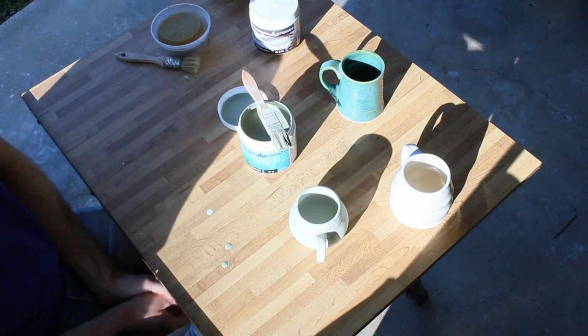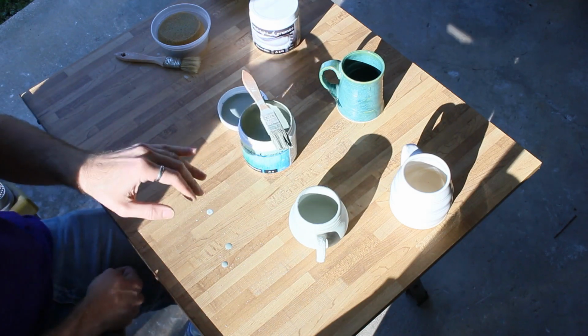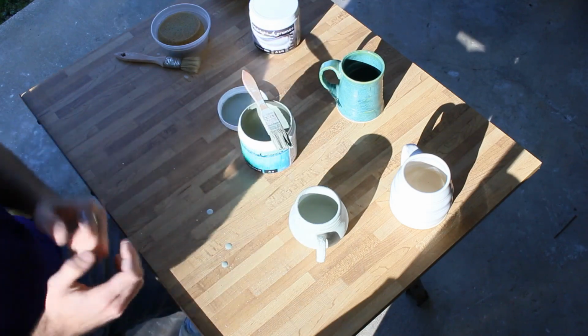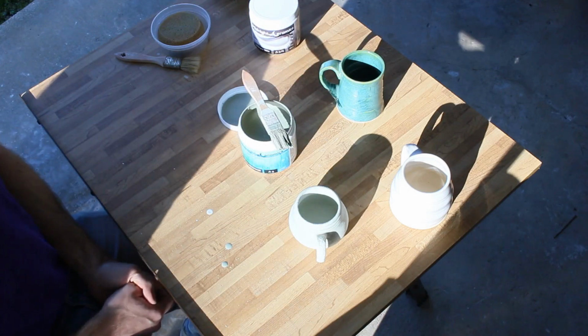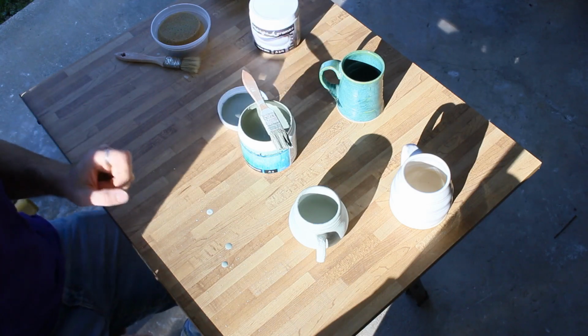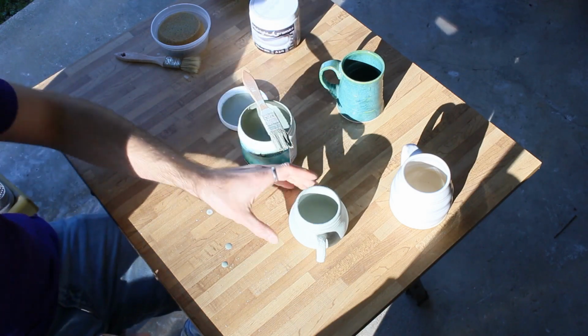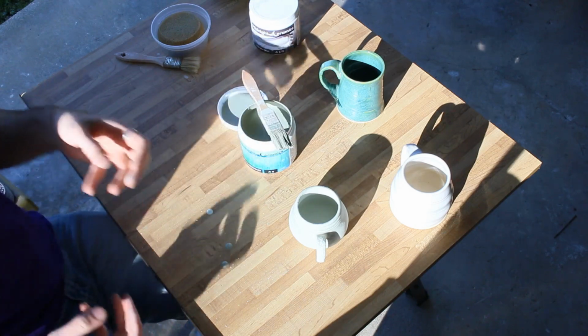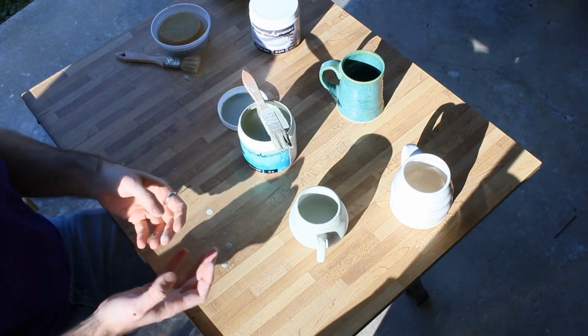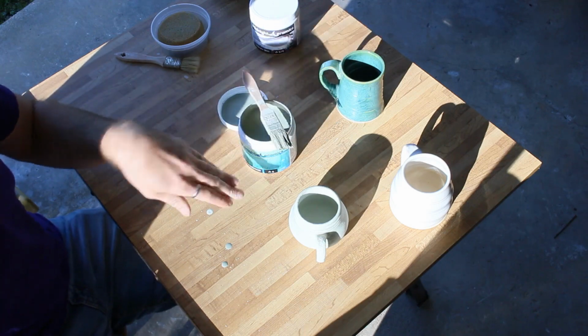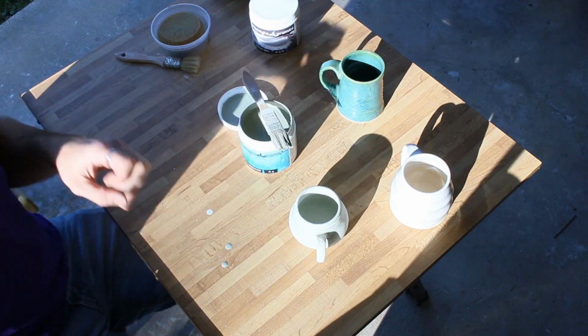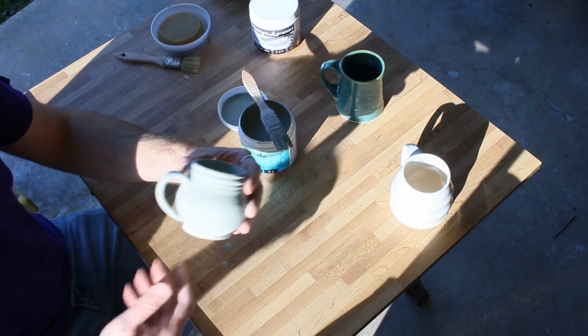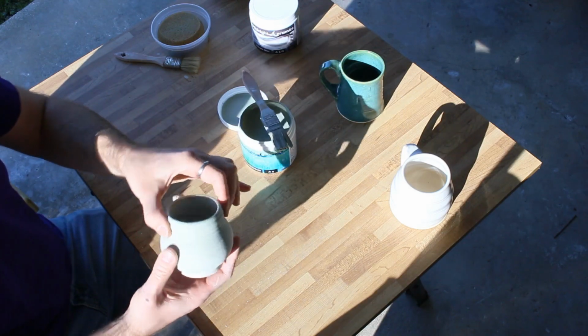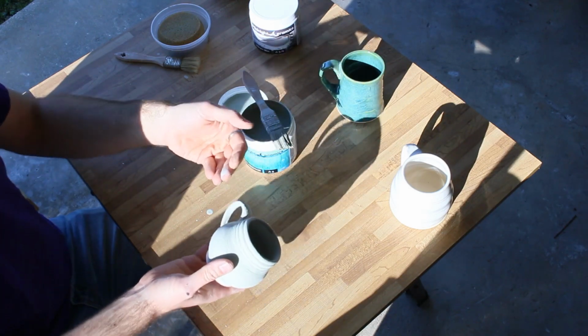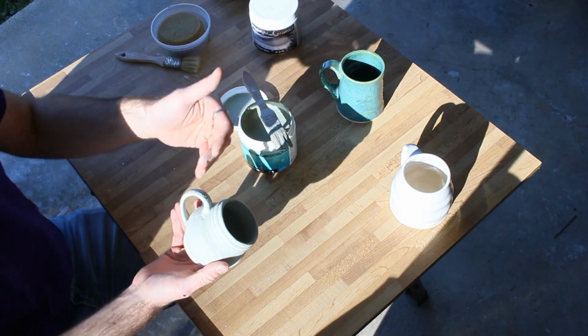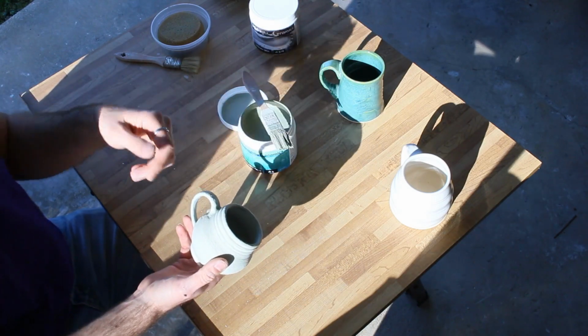So that's applying 1 glaze to 1 pot. I can talk a little bit about glaze defects as well, specifically trouble that you might run into while you're applying glaze to a pot. The biggest one that I tend to see is called crawling. And with crawling, what happens is people are applying way too much glaze to their pot, or for whatever reason, the water from the glaze isn't able to soak into the clay. So if it takes more than like a couple minutes for your pots to be dry enough that you can touch them, then there's probably too much water in the wall of the pot, or there's wax there, or there's like oil on the surface of the pot there, or maybe dust.